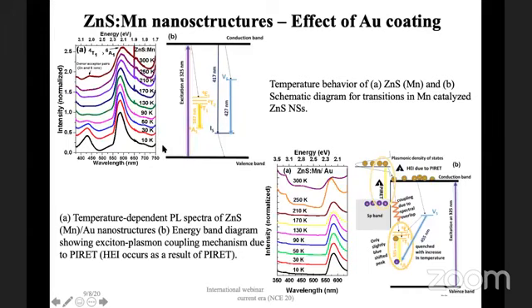Now I'm coming to the last part of my presentation. We did the temperature dependent study of zinc sulfide doped with manganese nanostructures. These two photoluminescence curves are taken from 10 K to 300 Kelvin with pure zinc sulfide. So there is no gold coating on these ones. You can see we see a very strong bluish line at low temperature, 10 K, and then we see a red line. We don't see much in the green over here. These are the transitions which we observe.